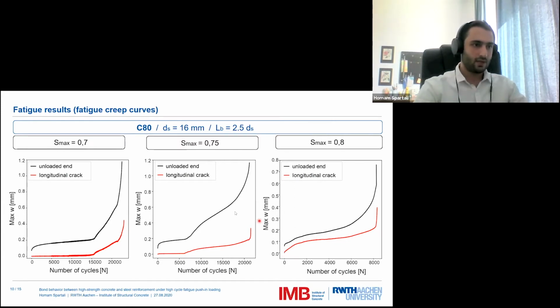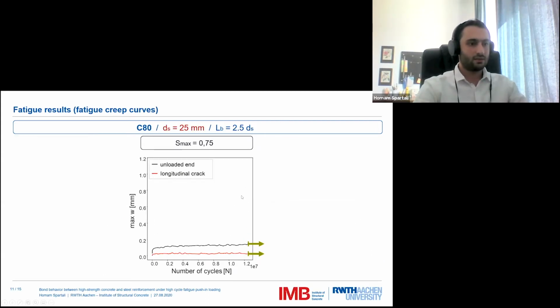first few cycles. The second thing that we can notice here is that the slip increases steadily until we see the emergence of the crack, which accelerates the slip value and leads eventually to the failure of the specimen or of the bond. Here's another test which lasted until 12 million load cycles without failing, which had the same parameters of the last slide, but with a diameter of 25 millimeters and a maximum load of 75.